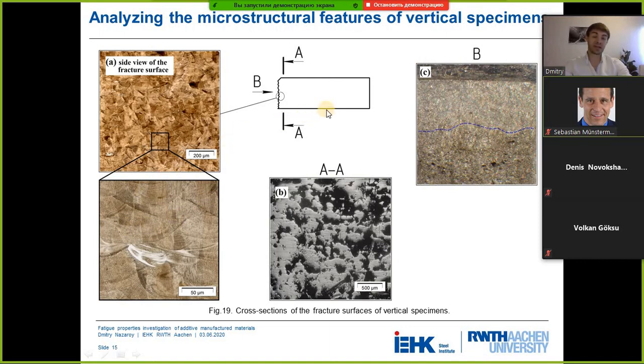And since the crack propagated coaxially with the elongated columnar grains, the crack cleaved down the length of the columnar grains, similar to chopping wood with an axe. And therefore the longitudinal distribution of the fracture surface was formed.